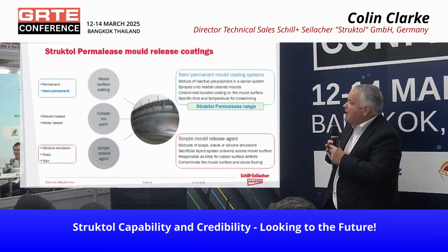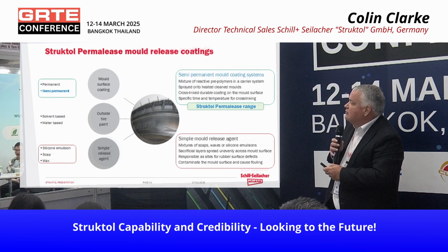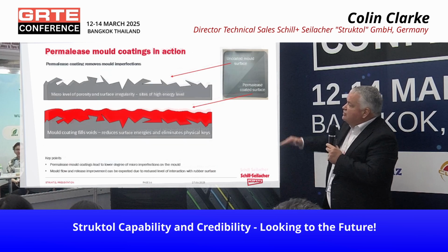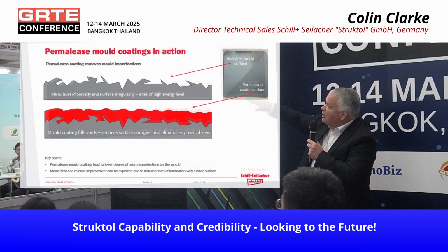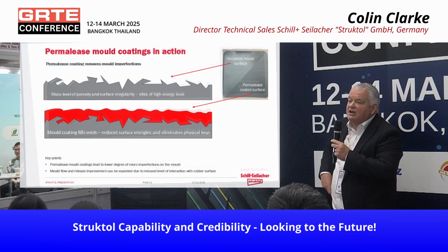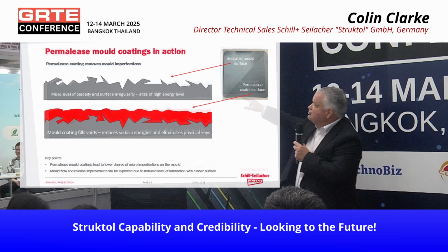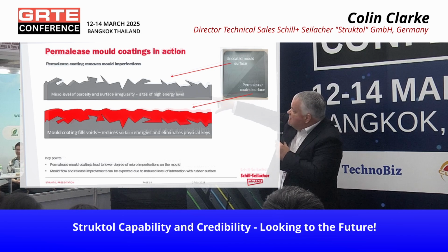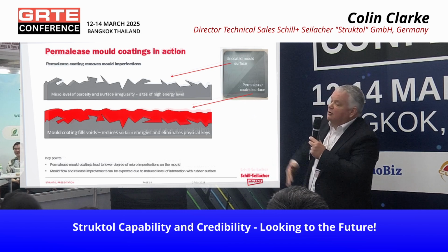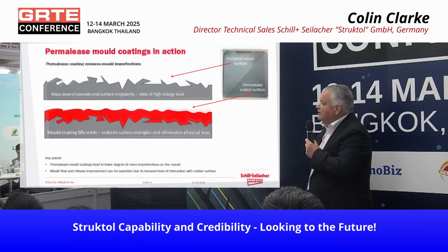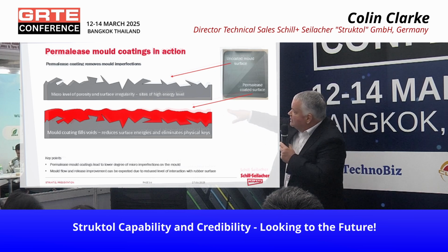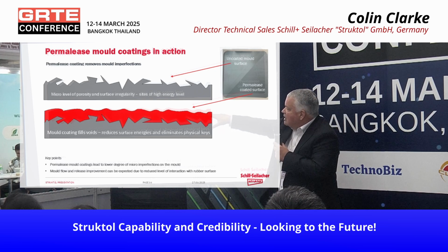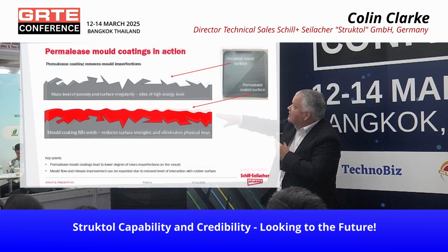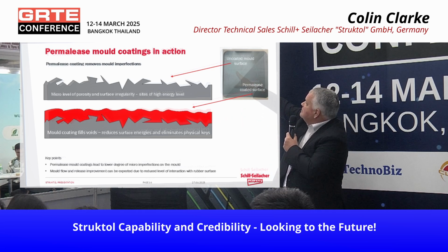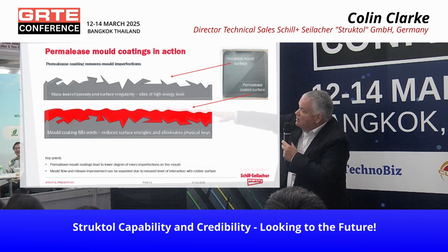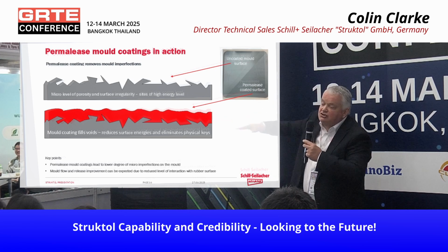So we'll talk a little bit about the advantage of this type of coating. Our aim is to really regularize, if you like, to make a high uniformity coating on the surface of the mold, to tune out, if you like, the micro irregularities and surface porosities that you'll see on the surface of a metal. So applying the coating really smooths that surface out, the coating cross-links, and really fills out the irregularities. So this would be an uncoated surface, this would be the coated surface with a much lower surface energy and surface friction.